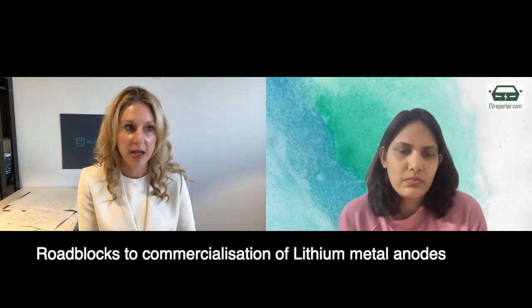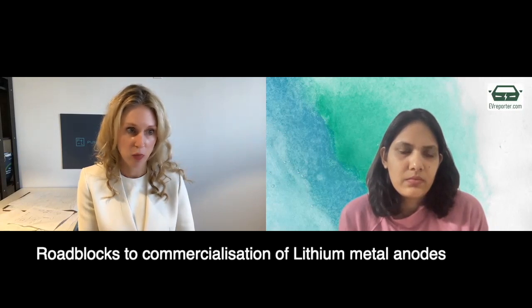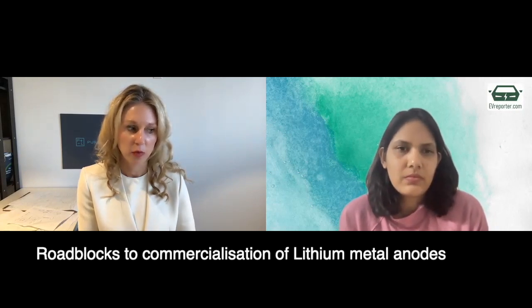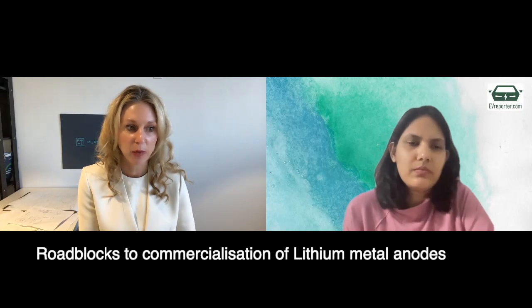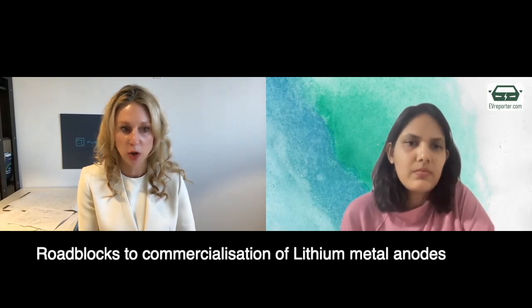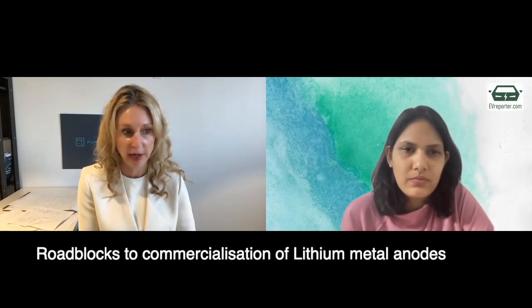And if you put lithium in the wrong situation with the wrong electrolytes under the incorrect current densities, it will grow dendrites and it will puncture right through any separator in anybody's battery. And that will, of course, lead to a thermal runaway and fire, right? Exactly. Which is not acceptable. So for this to be adopted en masse, it has to be so safe.